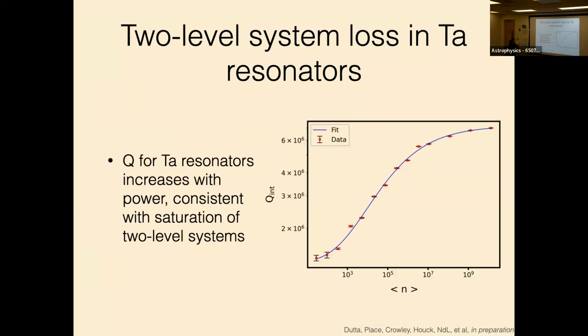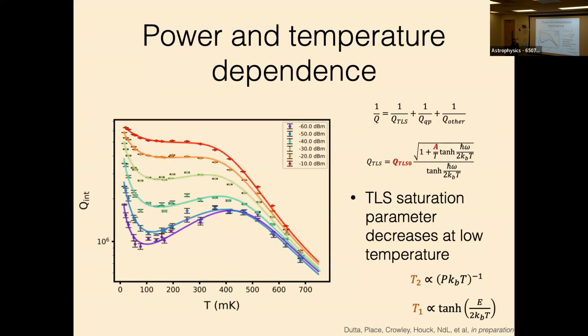So in these tantalum resonators, we're able to see evidence of this two-level system loss. You increase the power and the quality factor goes up, which means that you're saturating some loss. And this is something that I think is not generally done by the community, so this is very, very new data. But our approach to this was to say, well, we have some model for what our losses are.